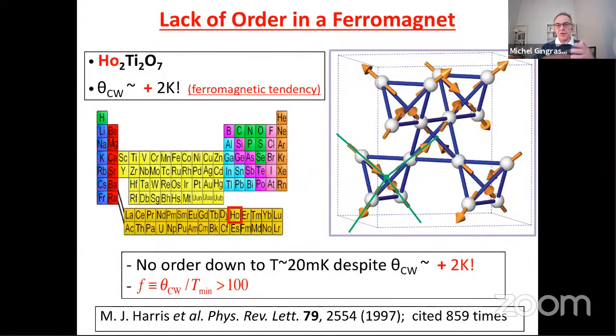But what they found through a number of measurements, such as muon spin relaxation, neutron scattering, magnetic measurements, and AC susceptibility measurements, was no sign of a phase transition in that system down to 20 millikelvin. This came as a surprise to them, because you have a three-dimensional system. The conventional unit cell is cubic, so it's not an anisotropic system. The interactions are overall ferromagnetic. You have an Ising system for which there should be no quantum fluctuations.